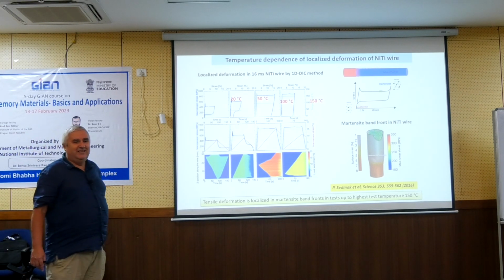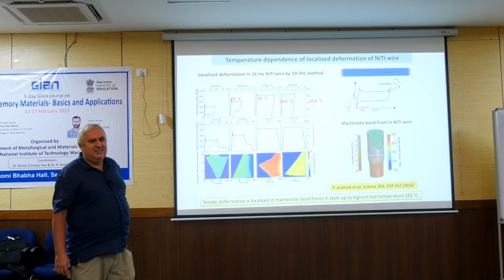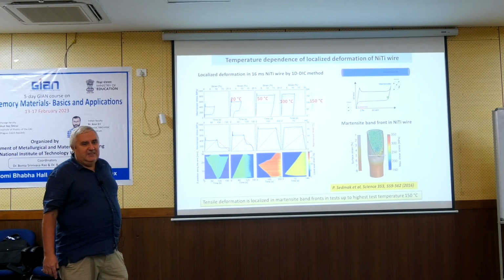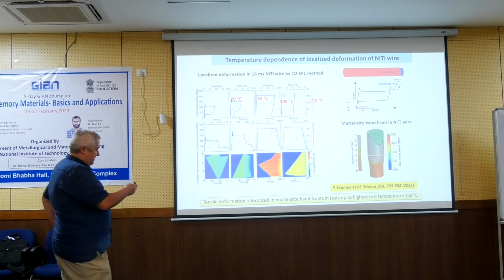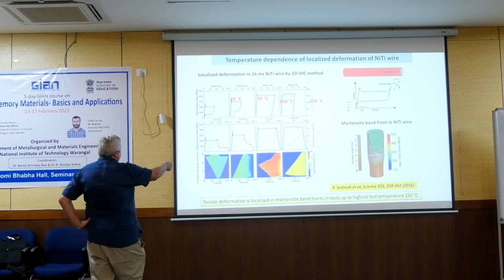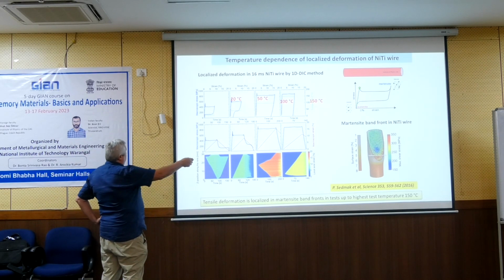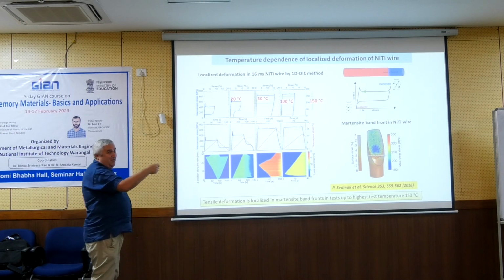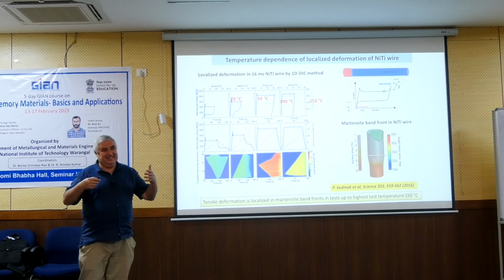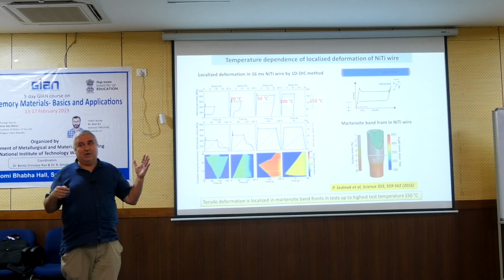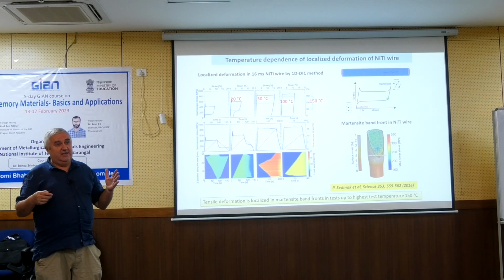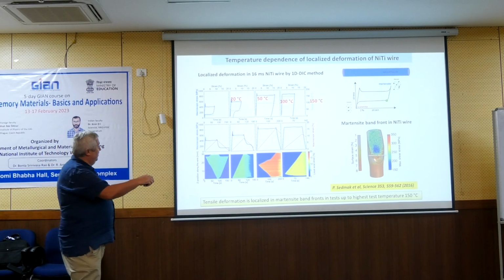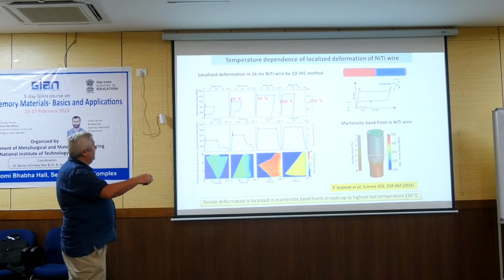In the case of rate dependent behavior, the total transformation of Martensite will not happen? No, I said that this is rate independent. This is not rate independent once you have the plastic deformation inside. There is no guarantee that it is rate independent. And the problem is, if we did the experiments also at, let's now shift it.